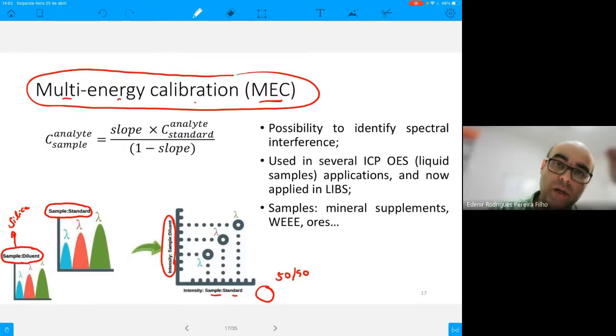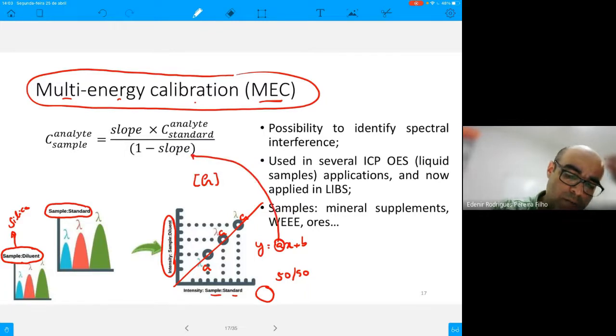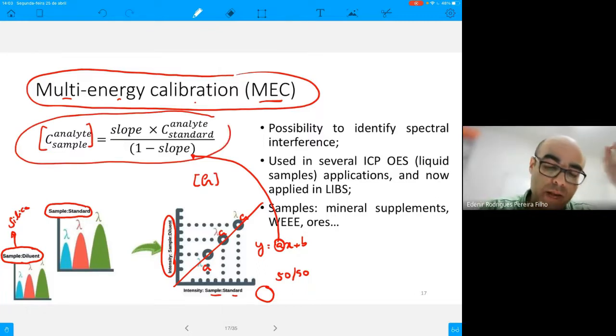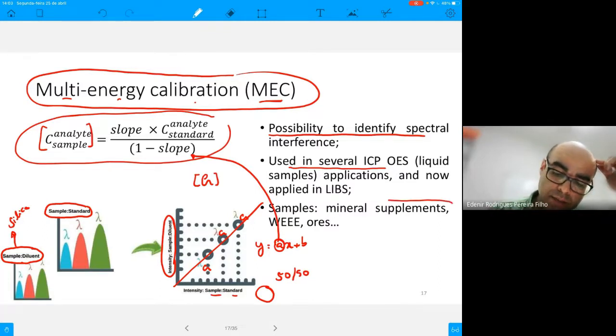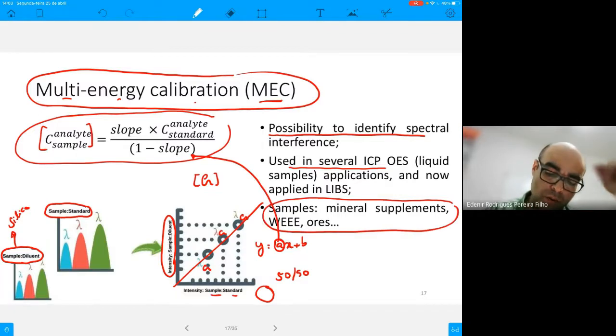And we collect several emission lines signals from the analyte. For example, if we are trying to determine chromium, we can collect several emission lines for chromium and produce a linear model. The slope of this linear model is used to calculate the concentration of the analyte in the sample by using this equation here. Using MEC, we can identify spectral interference. This strategy was used for the first time in ICP OES for liquid samples. And using LIBS, we analyze mineral supplements, electronic waste, and also ores.